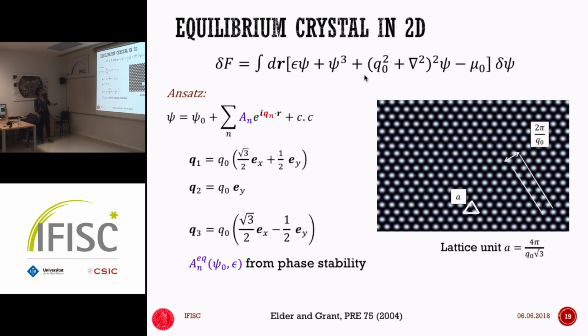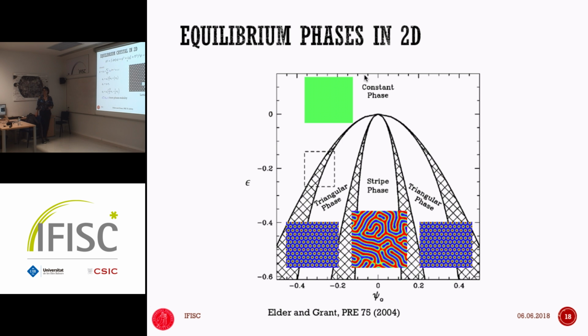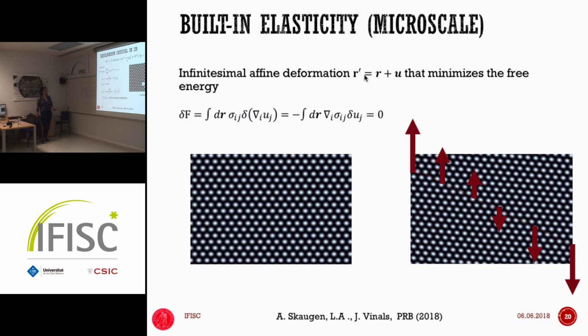All right. So at equilibrium, then this density field, which is also like an order parameter for the defects that we're going to study, in the one-mode approximation can be considered as a superposition of three waves with these wave vectors, and with an amplitude that is given by the quenching depth and the fixed density. And it's taken out from the stability phase diagram that we had before, okay?